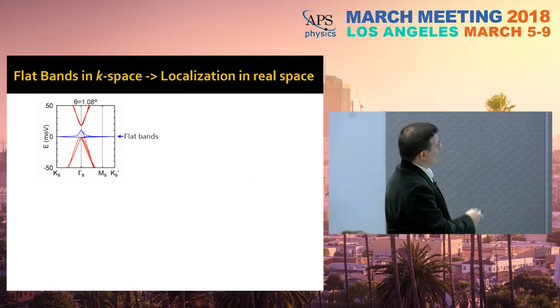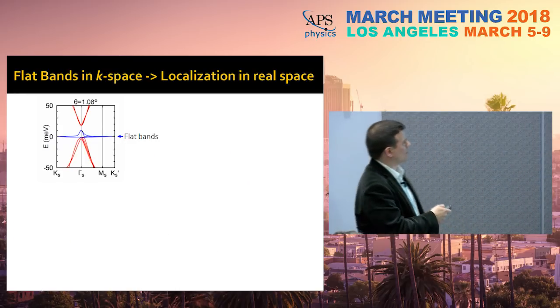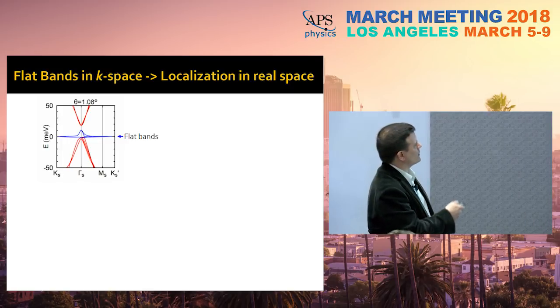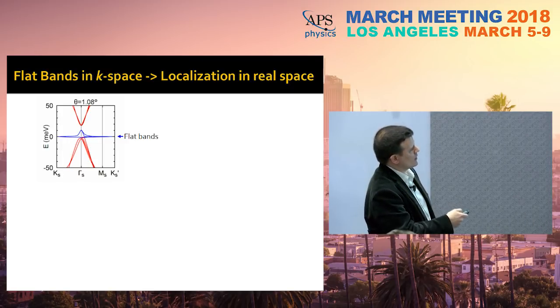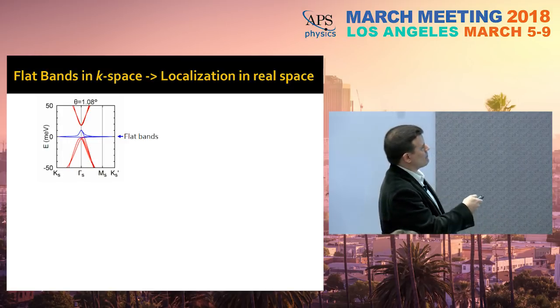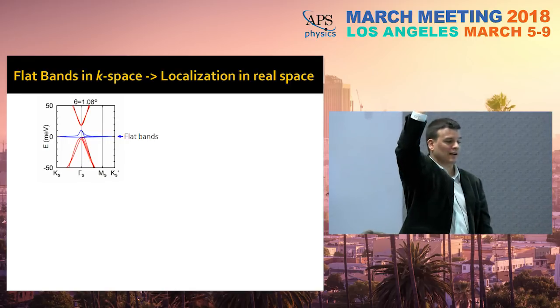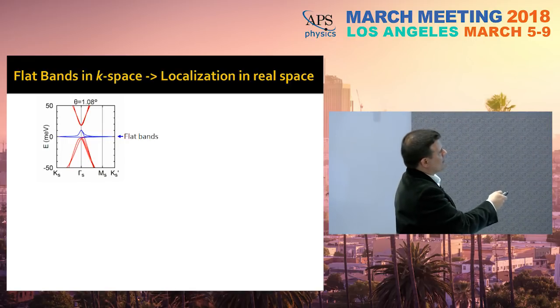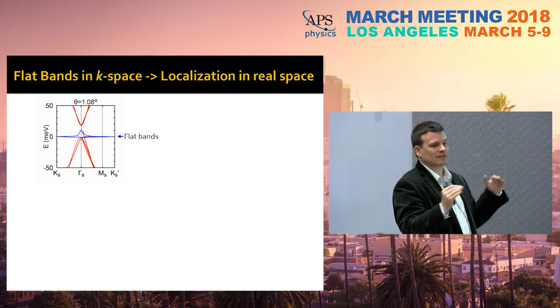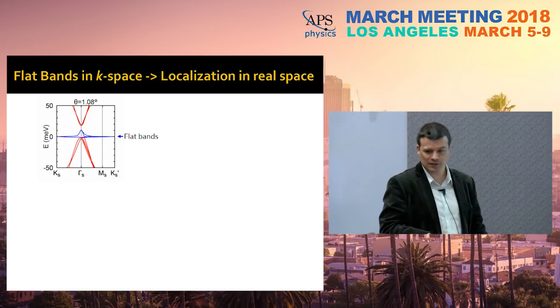Now, this is an actual cut of that band structure for 1.08 degrees. This is energy versus momentum. You see, this is not 100% flat, but the bandwidth has been decreased from several electron volts in graphene down to about 10 millielectron volts now. These bands are very, very flat compared to the original Dirac bands.